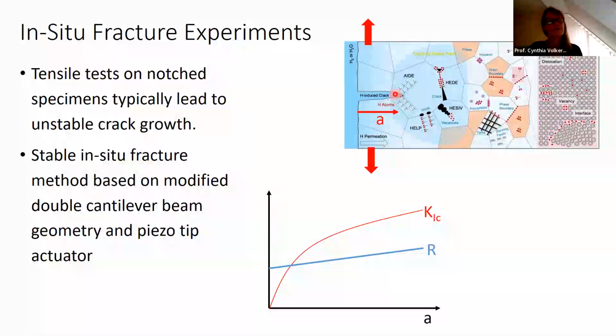And if you think about a thin sheet of say, aluminum foil that people use in the kitchen, if you pull on that, you know that it will rip, that once you start a crack, it will fail very easily. And that's a statement of what I'm showing here, is that as soon as you have a tear in that material, that crack then propagates very easily, even though aluminum is typically a very ductile material. And if you were to think of working with it, at the bulk level and not of a thin film, for instance, you might expect that there would be ductile deformation and not sort of propagation of a failure crack.